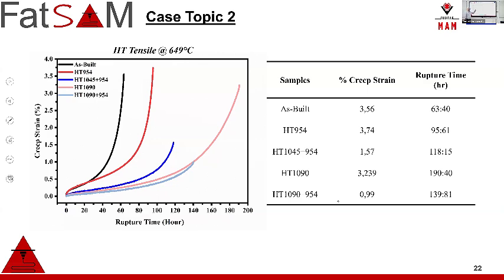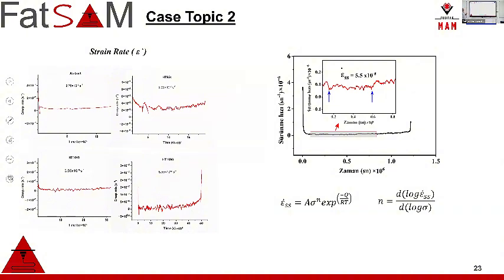Another issue for 939 and 718, any of these materials, let's say that it's prolonged in these harsh conditions is 140 hours, they will replace half of this cycle. They will be replaced. So if there is no plastification, no micro cracks, no crack propagation, no fracture. Let's go to results. Why I'm saying this?